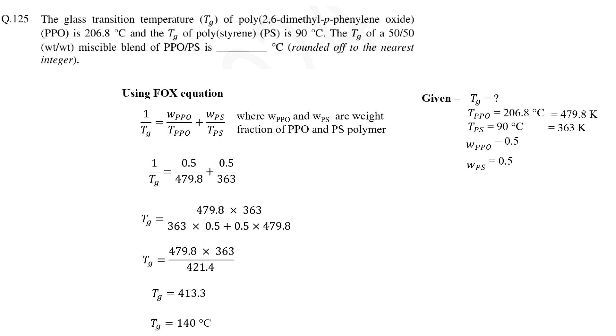On a side note, if you see the question it mentions that it is a miscible blend, but this can become a tricky question if it says it is an immiscible blend. In that case there will be two Tg's — both 206.8 degrees Celsius and 90 degrees Celsius — because each polymer will form separate domains and they will retain their own Tg.